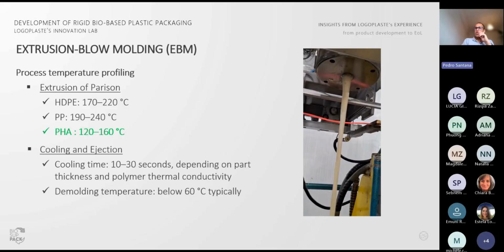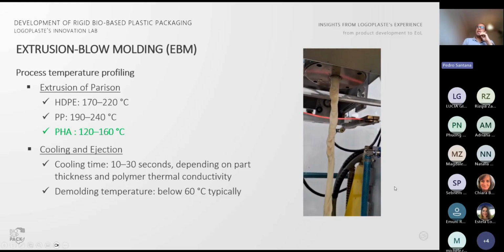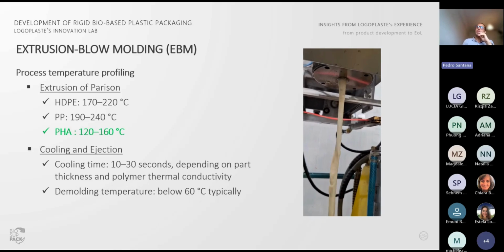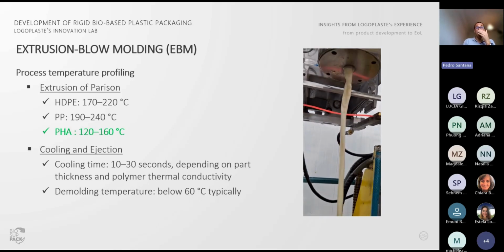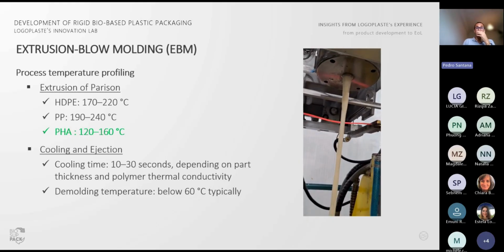However, when these same conditions are applied to alternative materials, such as certain grades of PHA, the extrusion of parisons can become very unfeasible, as you can see here in the image. You can see that the material is quite fluid, and it was impossible to form a stable and blowable parison.